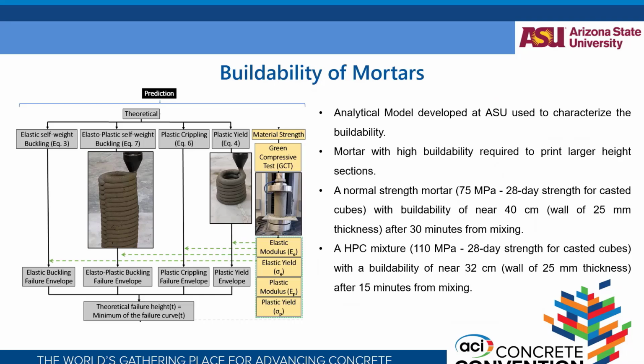While printing walls, the biggest thing we initially have to check is buildability, to make sure that we can build to the height that we require. So we have built an analytical model at ASU to characterize buildability based on the green strength of the mortars. We use that model to predict the buildability for different mixes that we tried. We finalized 2 different mixes that we are going to use for the study.